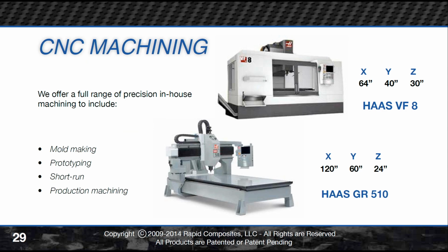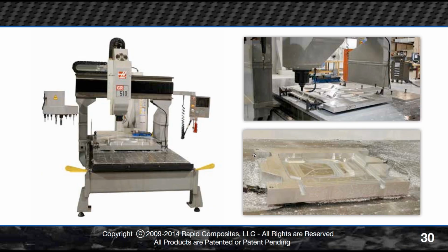This will give you an idea of the typical kinds of machining centers that we work with, with big, accurate build envelopes. And a lot of the time, in most cases, it's matched metal tooling. I would say about 80% of the time when we're talking about mid-range volumes. The way I describe mid-range volumes would be anywhere from about 200 units per annum to 5,000 units. And assuming there's adequate draft on the molds, we can typically get 5,000 shots out of a single aluminum tool set, assuming they are plated.